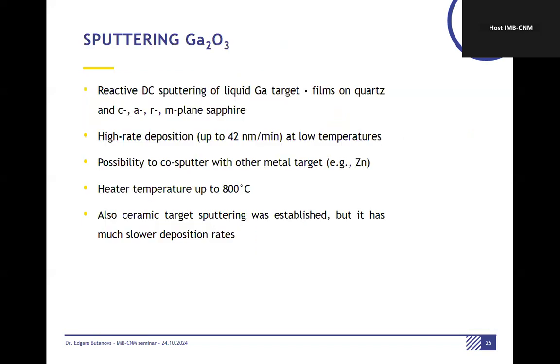Okay, and then the sputtering part. Sputtering is what we have explored the most. We have developed a novel technique based on a liquid gallium target. I will show some more details of what we have done. We can obtain very high deposition rates. This is mainly at room temperature, so it's interesting mainly for amorphous films. We can do co-sputtering, which we do with zinc. I will also show you some results.